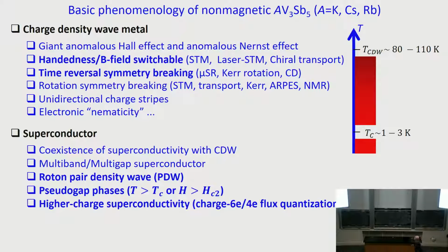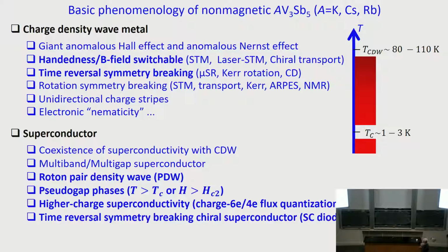And then there is this really anomalous or exciting phenomena, that is the higher charge superconductivity detected by higher charge flux quantization. More recently, there are some experiments looking into the diode effect, and they concluded that the superconductor breaks time reversal symmetry as well, and probably a chiral superconductor. So I want to call these extraordinary superconductors, because I can't use unconventional superconductors anymore, because that is sort of reserved for superconductors that are there because of electron-electron interaction rather than phonon-mediated superconductor. I should say there is no evidence so far that points to this superconductor to be non-electron-phonon driven, right? But all the quantum phenomena can be just as interesting as extraordinary.